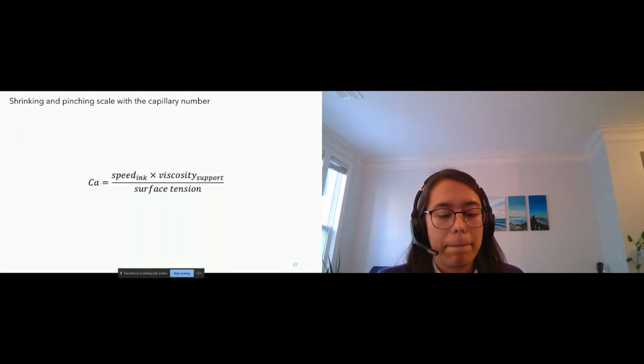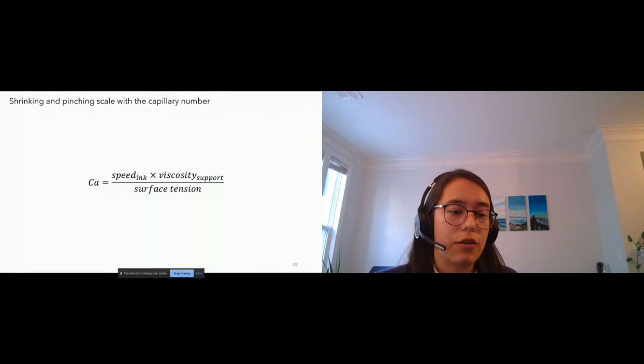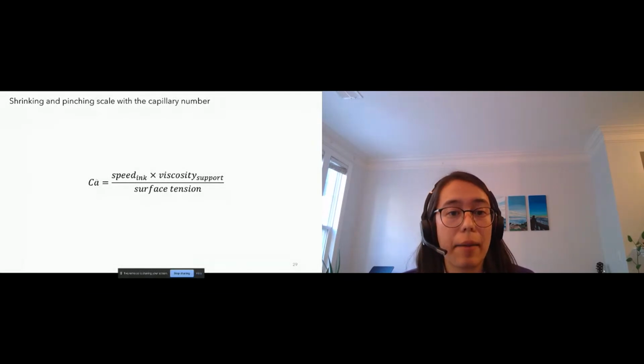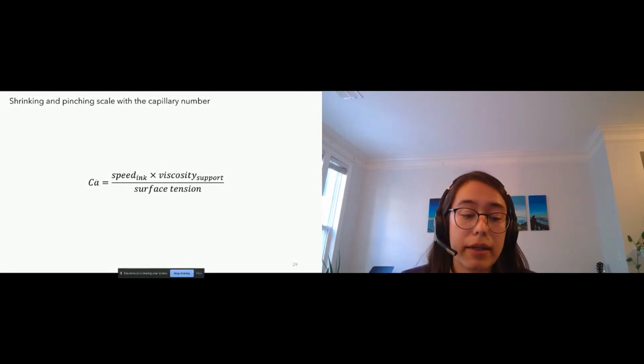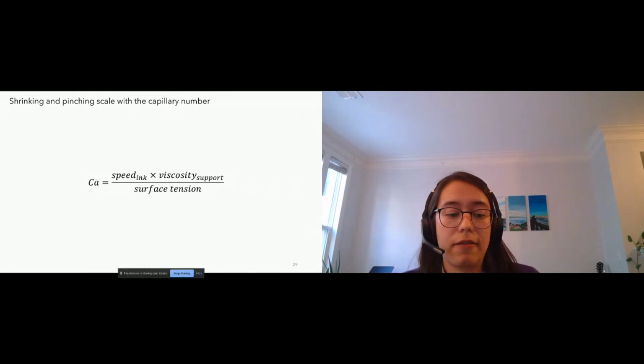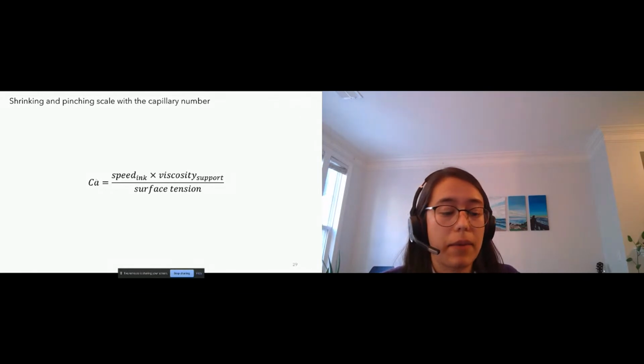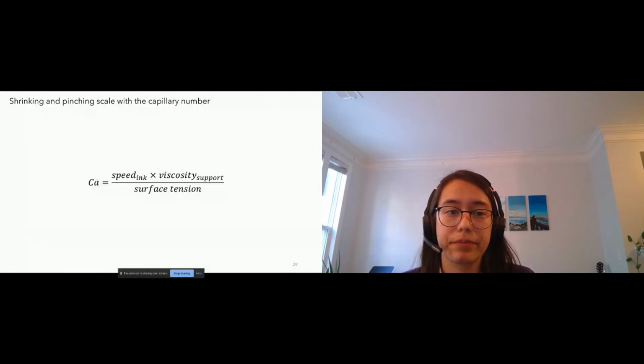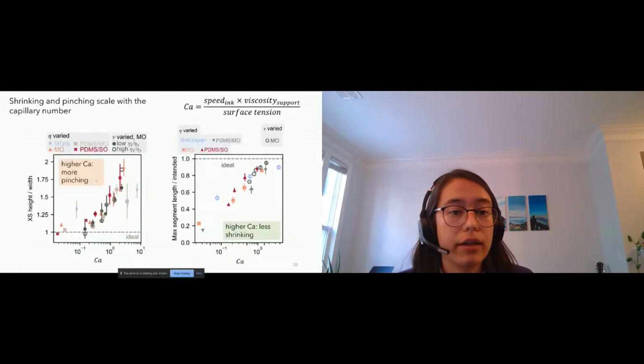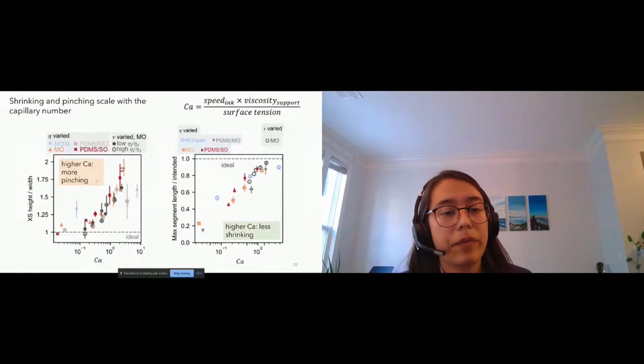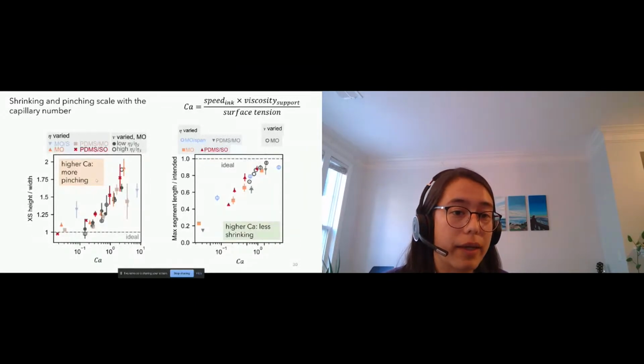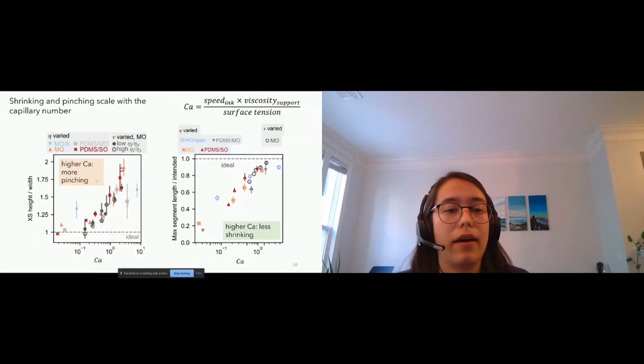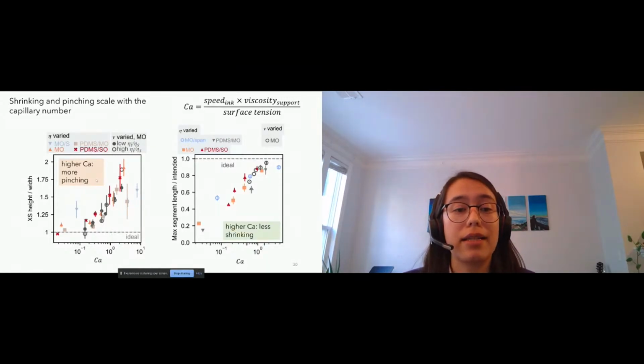So in order to map these oil-based inks onto some sort of constitutive relationship that tells us how we can balance all of our properties, we can use the capillary number. So that's the speed of the ink times the viscosity of the support divided by the surface tension. So that capillary number is telling us how we need to balance the viscous dissipation in this system against surface tension. So here you can see that as we increase the capillary number, we get a taller cross-section height over width. And so that's telling us that we get more pinching as we go to those higher capillary numbers. So that's less than ideal.